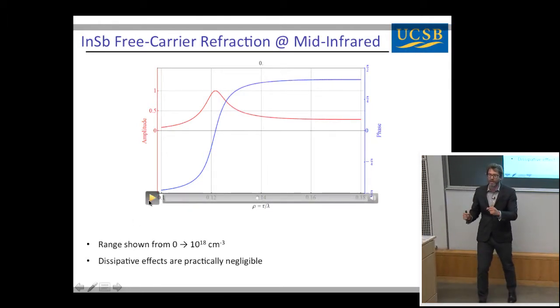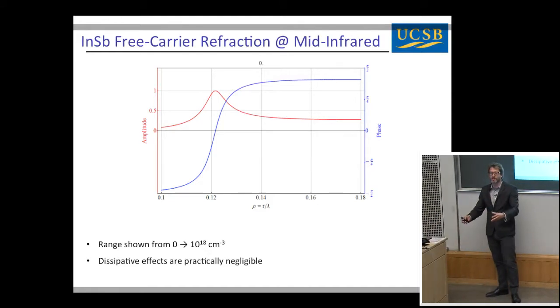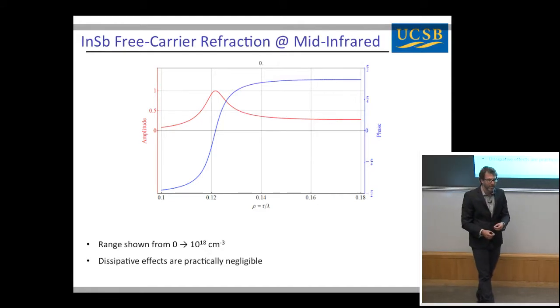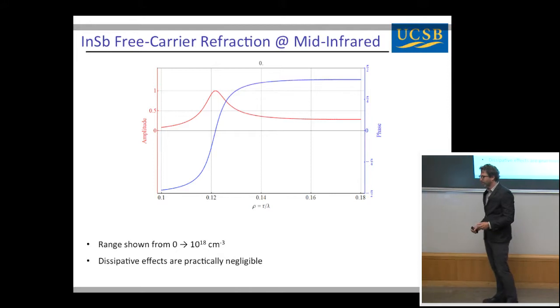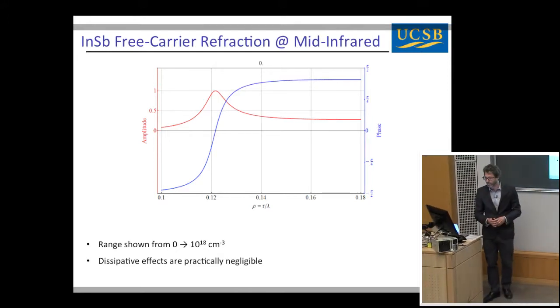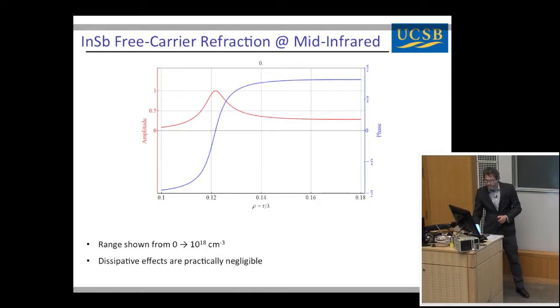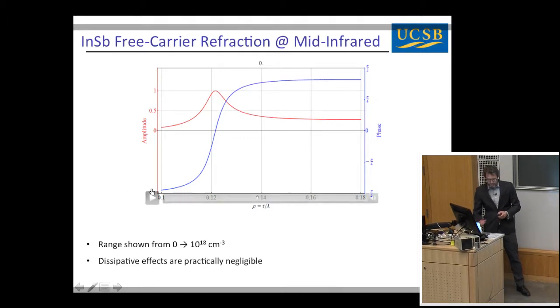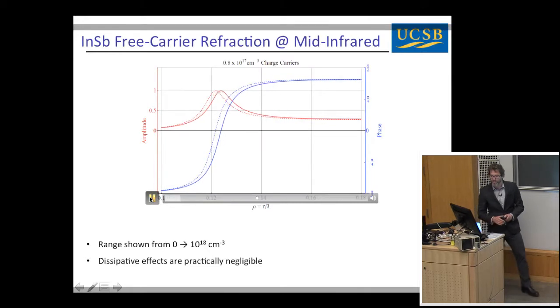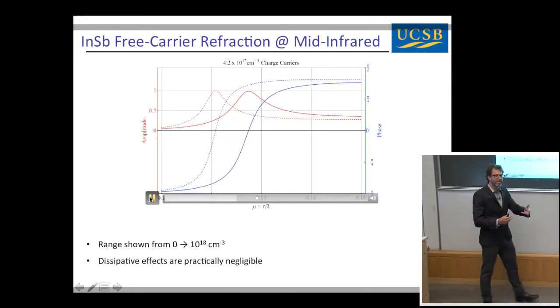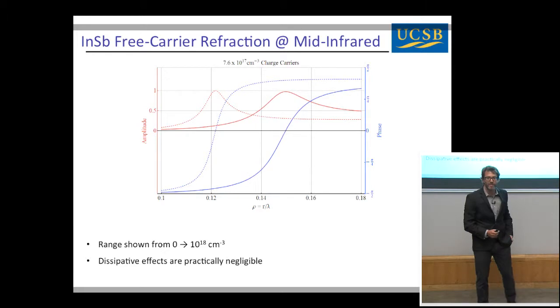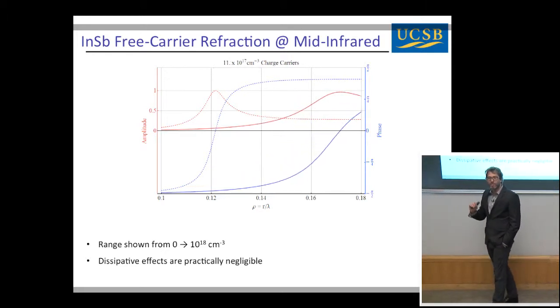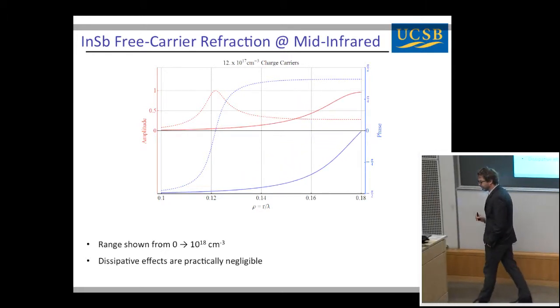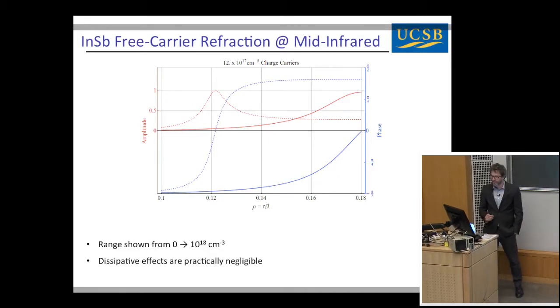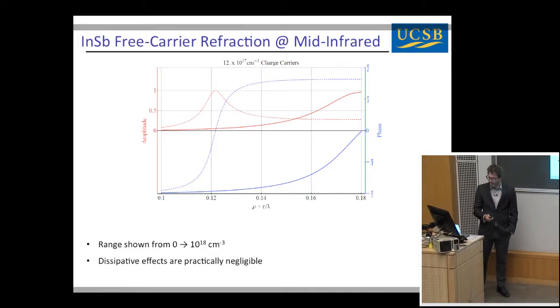So what I want you to look at when you see here is that everything shifts to the right, okay? So we're reducing the refractive index of the material, which is analogous to, in a sense, making it smaller. So our resonances shift to higher frequency or shorter wavelength, okay? And I also want you to notice the amplitude of this peak in the red, which stays relatively constant. So even though we're introducing free carriers, actually the dissipative effects are minimal, and the amplitude of the response stays roughly the same. And I'll talk about this particular value that we're seeing and what it means.